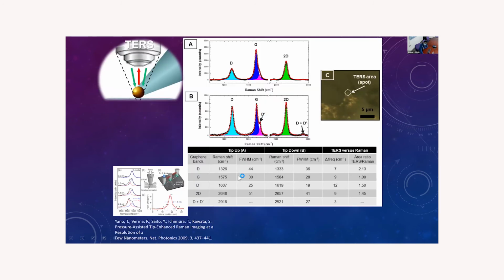In this case, we analyze the spectroscopic features of the sample, and we get that when the tip was touching the sample, we get a higher intensity of the 2D and a lot of small features here that could be due to the enhancement of the gold nanoparticle to the sample, but also, as in this case, to the deformation of the graphene due to the pressure applied by the tip.